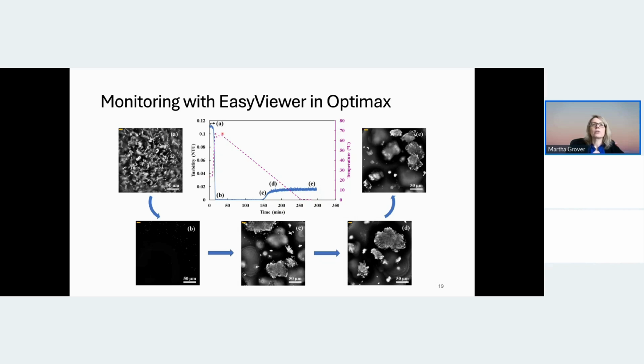And so we make crystals, and then we dissolve them, and then we make crystals here. You can see in the Easy Viewer, we start off with some material, we dissolve it, and then we form crystals. They're sort of a plate-like crystal, and we don't see obvious changes in the morphology as the crystals grow here. This also allowed us to have more material that we could use for characterization. But in all cases, we always saw the same sort of XRD pattern that we associated with Form 2.